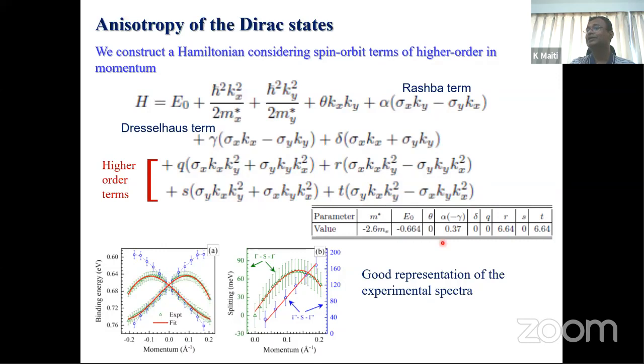Okay. And you can see that close to the Dirac node, they are giving you isotropic behavior. These blue ones are along one k vector, the green ones are along another k vector. The symbols are experimental points, and they show the isotropy close to the Dirac node, but far away they are anisotropic.